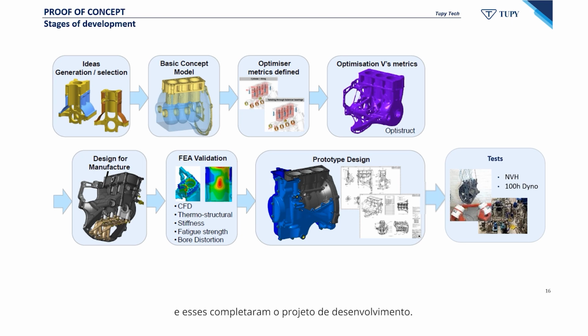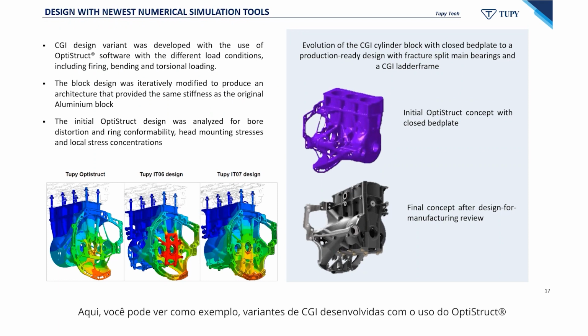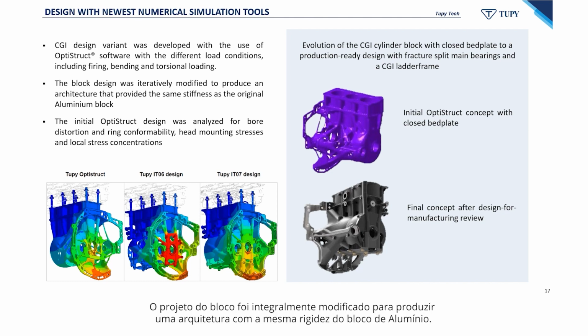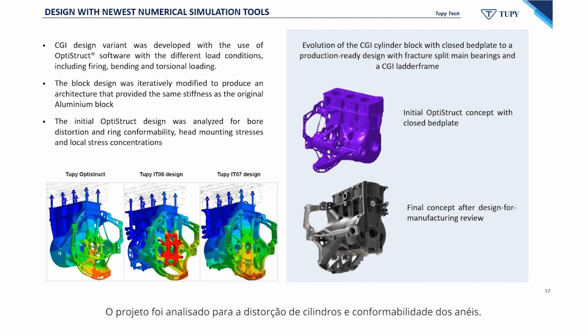Here you may see as an example various CGI design variants developed with the use of OptiStruct and with different load conditions, including firing, bending, and torsional loading. The block design was iteratively modified to produce an architecture that provided the same stiffness as the original aluminium block. The design was analyzed for bore distortion and ring conformability and for head mounting stresses and local stress concentrations.